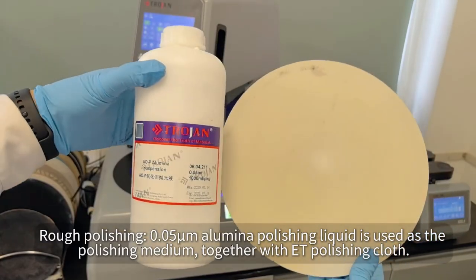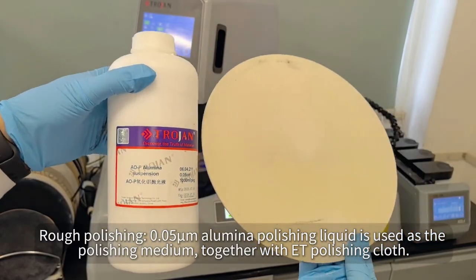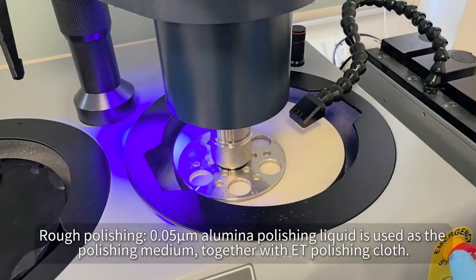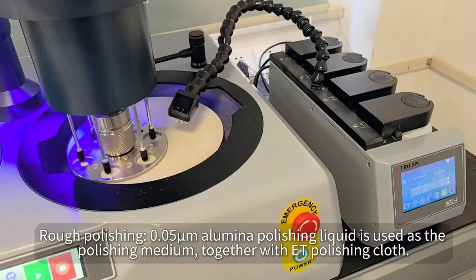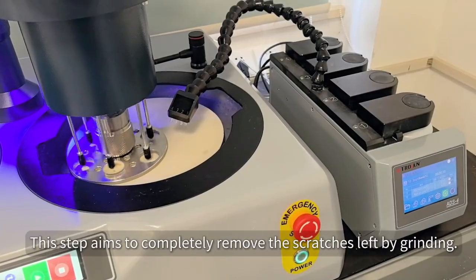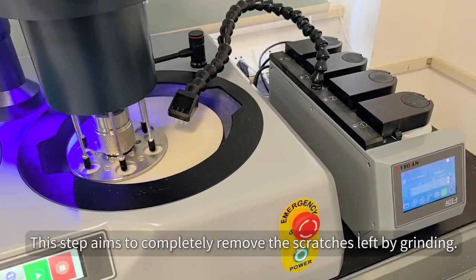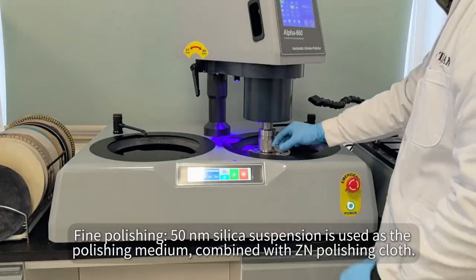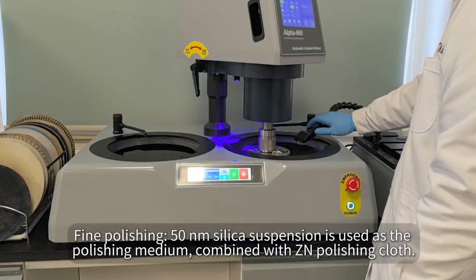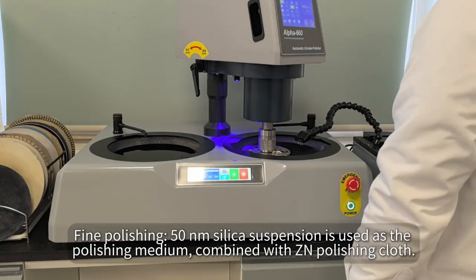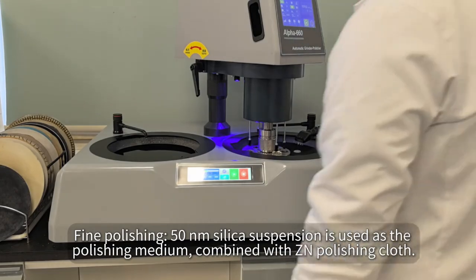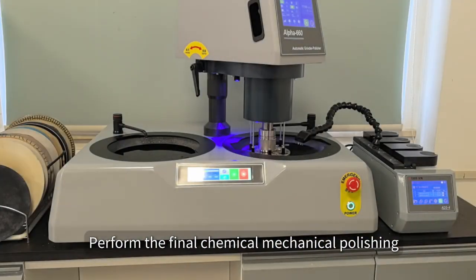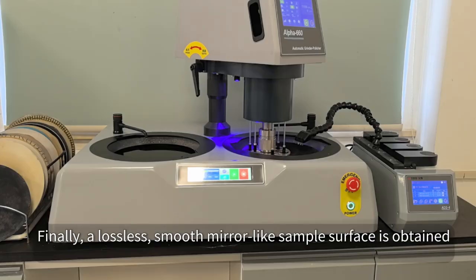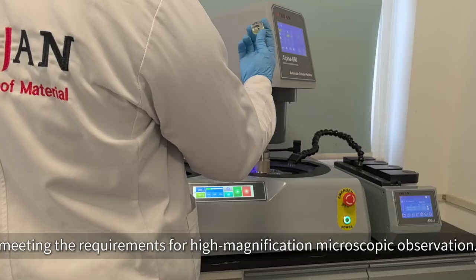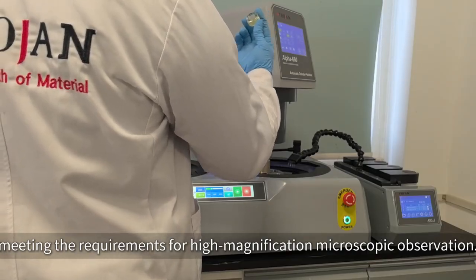Rough polishing. 0.05 micrometers alumina polishing liquid is used as the polishing medium, together with ET polishing cloth. This step aims to completely remove the scratches left by grinding. Fine polishing. 50 nanometers silica suspension is used as the polishing medium, combined with ZN polishing cloth. Perform the final chemical mechanical polishing. Finally, a lossless, smooth, mirror-like sample surface is obtained, meeting the requirements for high magnification microscopic observation.